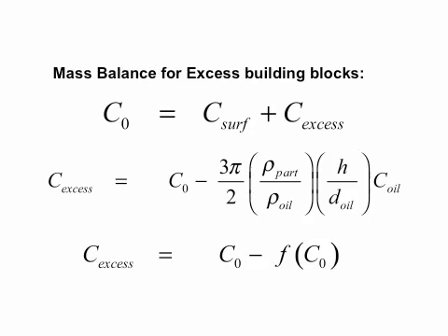So I can basically revert that a little bit. I could say, okay, the amount of clay that's in the water phase is the amount I put in minus the stuff that gets adsorbed. With the rearrangement of the equation on the previous slide, you can calculate how much is adsorbed if you assume it's full packing. So what you're left with is this expression that links it to the concentration of oil droplets. And because we had this reversible partitioning, you could even argue that the second term, the diameter of the oil droplet, would scale with the amount of clay that I put in. So you could argue that the amount in excess in the water phase would be what I put in minus a function of what I put in. And that should match quite nicely.